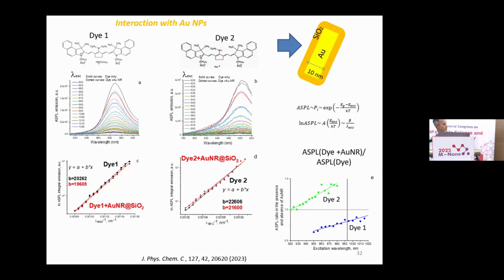So the structure of these dyes is shown here. They differ by mesogroups only. You can see here the amino group, and here two phenol groups linked via nitrogen to the molecular backbone. And we study anti-Stokes photoluminescence, when we excite with smaller energy than the emission. And we compared the emission of the dyes without plasmonic nanoparticles, shown by solid curves, and emission of molecules in the presence of the plasmonic nanoparticles, shown by dotted curves.